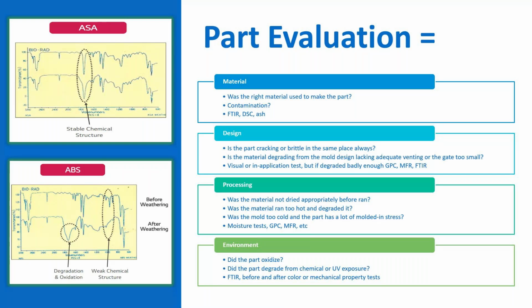So that's a problem. But what would happen then is if I don't dry it appropriately, if I don't do the moisture test, I could turn around and do a test to figure out if I degraded it greatly because of hydrolysis. So I could do the melt flow test potentially, or the solvent viscosity test, or GPC if we have it, but determine if we had that type of degradation coming and apparent.